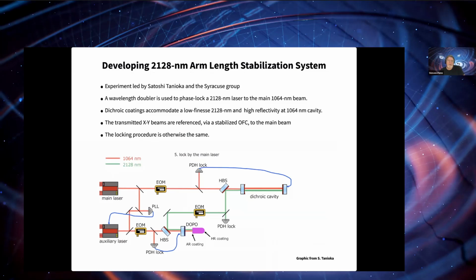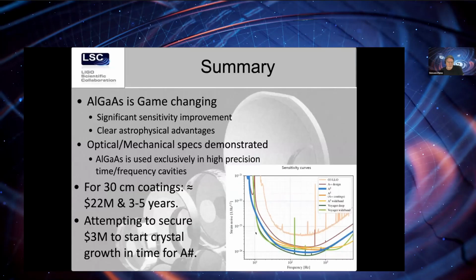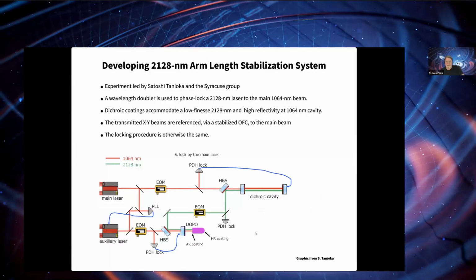In addition, there's an experiment that's occurring at Syracuse that's being led by Satoshi Tanioka about developing an arm-length stabilization system. Because of the band gap in AlGaAs, we can't use the green laser light to stabilize the arm cavities. So instead of using a frequency doubling, we're using a wavelength doubling technique. So locking a 2128 laser to the main 1064 laser and using dichroic coating so that we have a low finesse 2 micron and high finesse 1 micron cavity. And then basically the same system that is currently used to lock the arms in LIGO will be used. You're just using twice the wavelength instead of half. But the same locking procedure occurs.